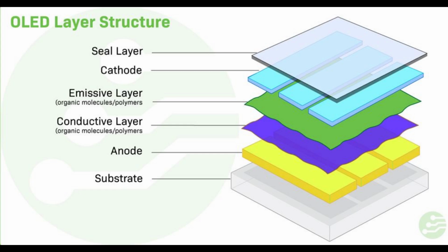Using deuterium instead of hydrogen, in other words deuterated compounds, in red, green, blue and white OLED light-emitting material layers and other layers nearby in OLED displays can improve their brightness by up to 30%. This is achieved by improving the current handling capacity and lifespan of these materials. Making indentations shaped like lenses on a transparent layer through which light passes from an OLED light-emitting material reduces the amount of scattered light and directs it forward, improving brightness.